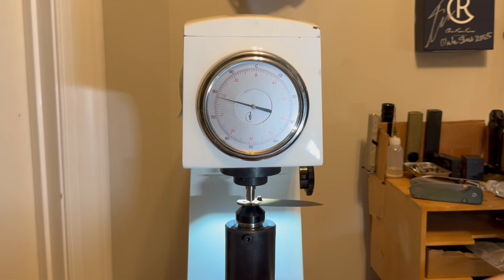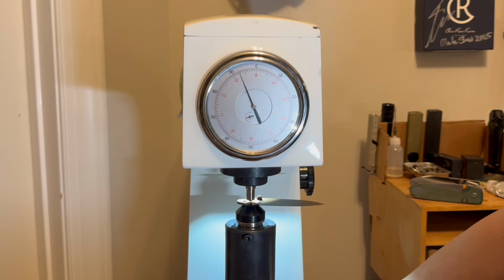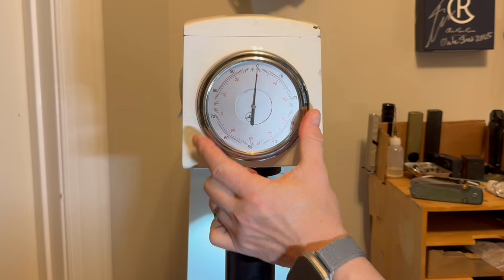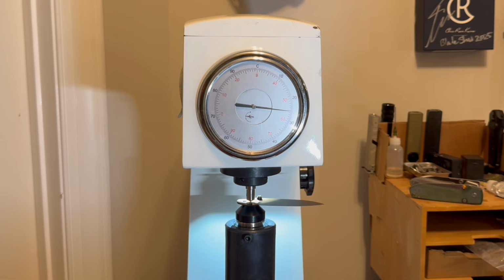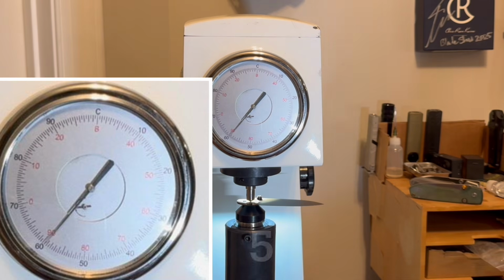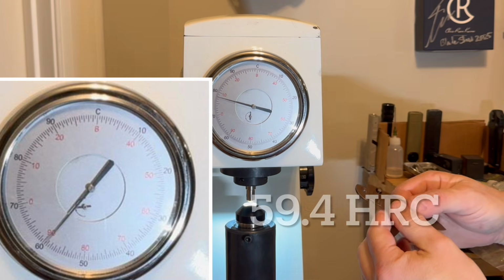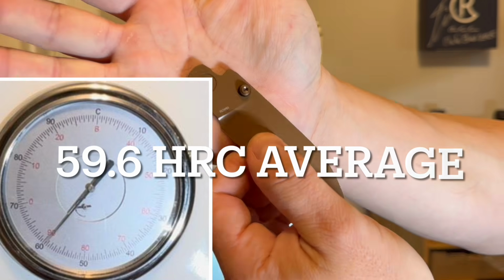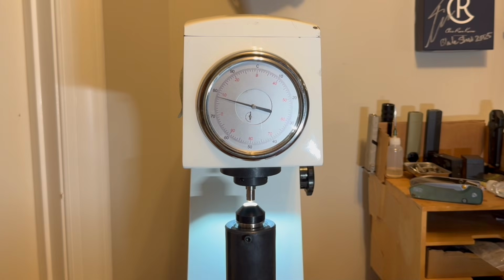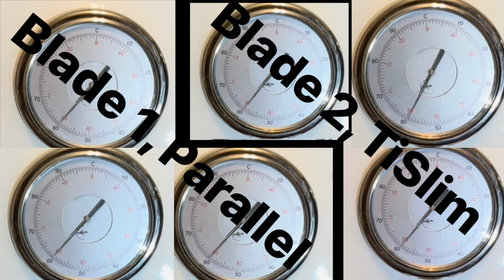This steel was actually brought into the knife world to sort of supersede 440C steel, because at the same hardness it will have a lot higher edge retention than 440. 59.4 on the third poke, and 59.6 is the average. So because the difference between the two blades is minimal, I can declare that whoever did the heat treat and then the coating knew what they were doing.